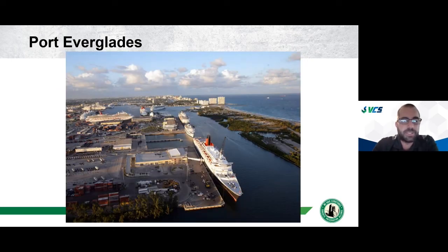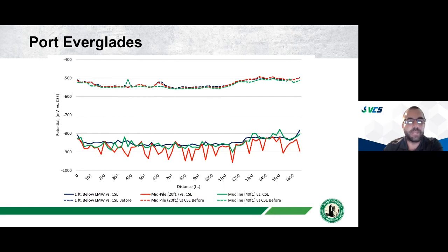Another marine structure, this is Port Everglades over in the Fort Lauderdale area. We did corrosion potential surveys of the bulkhead walls in these berths because they had a galvanic CP system. So we use corrosion potential measurements to verify that it's working properly.